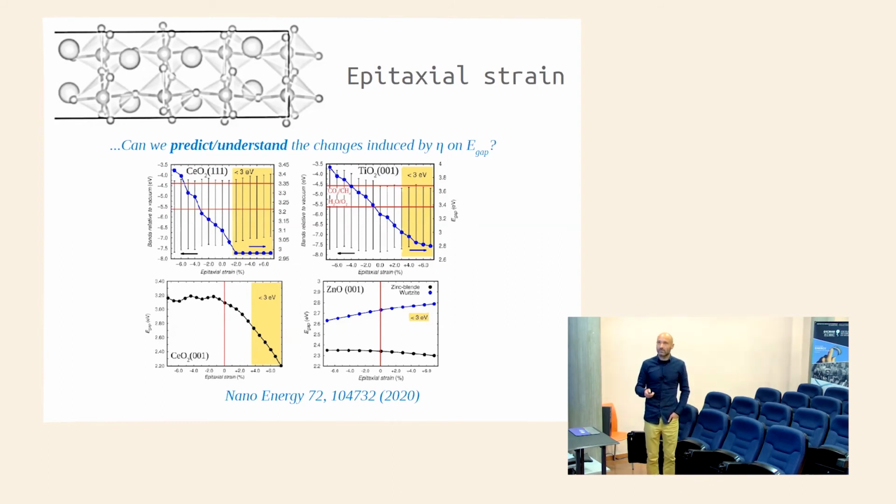As you can see, again, I mentioned there is quite a large difference in the behavior of the energy band gap. Now I'm going to focus on the energy band gap, because we were not able to find any systematics in the band alignments, and also to simplify the analysis, right? So for the same material, applying the stress in different planes presents a completely different reaction from the system. And when you compare different materials, the trends can be totally different, right? So can we understand this somehow?